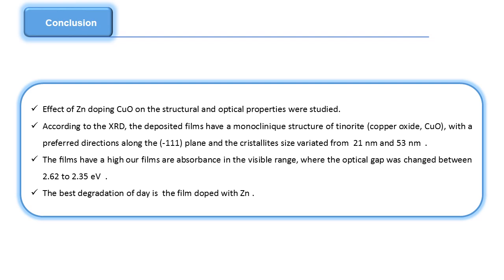Conclusion. The aim of this work is to study the effect of zinc doping of copper oxide on structural, optical and catalytic properties. According to XRD, all films present the formation of the tenorite phase of monoclinic structure with space group C2/c, with crystallite size varying between 21 nanometers and 53 nanometers.